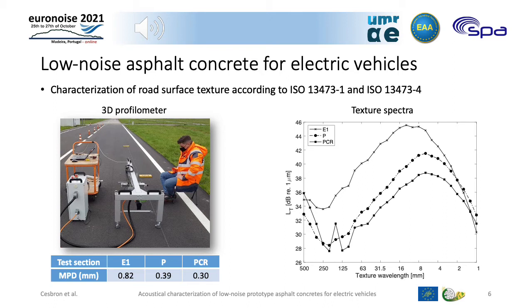On the right hand side of the slide you can see the texture spectra for the 3 test sections. As you can see, the texture levels of section P are up to 3 dB higher than those of section PCR at wavelengths lower than 125 mm, with an opposite situation at wavelengths greater than 250 mm. Texture levels of both prototype test sections are much lower than the reference E1, especially at wavelengths higher than 16 mm, for which a difference of about 6 to 9 dB is observed, respectively, for P and PCR.